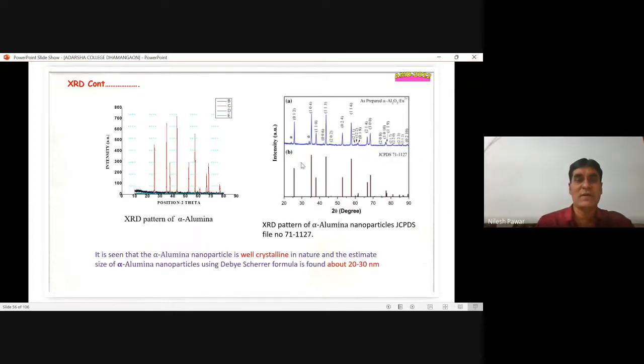This is the XRD pattern of my alpha alumina. We have synthesized the alpha alumina, and we compare this alpha alumina with the standard data. These are the standard data. The XRD pattern of the alpha alumina nanoparticle is compared with the JCPDS file number 71-1127, and these two are exactly close with each other, and hence these two are in good agreement. So our synthesized nanoparticle is good for the research.